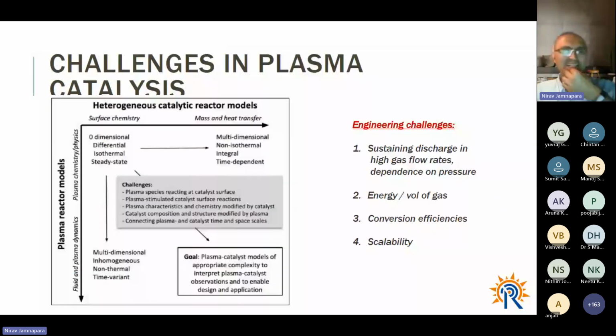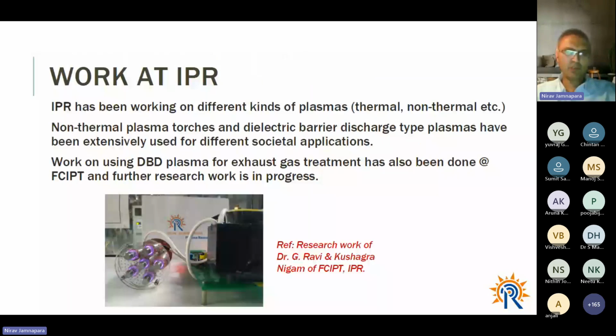For example, there are heterogeneous catalysis reactor models and there are plasma reactor models, and both have their own pros and cons. The engineering challenges are sustaining discharges and high gas flow rates, dependence on pressure, energy per volume of gas is very, very important, and the conversion efficiencies are very, very important. Scalability is another factor which will play a vital role in deciding which process dominates the market. So we have worked, and you can see here the purple glow discharge in the small device, which is indicative of the glow discharge plasma that we have developed for exhaust gas treatment, conditioning, for NOx and SOx removal. And the same plasmas are applicable for the same fuels, CO2 to synthetic fuel applications.